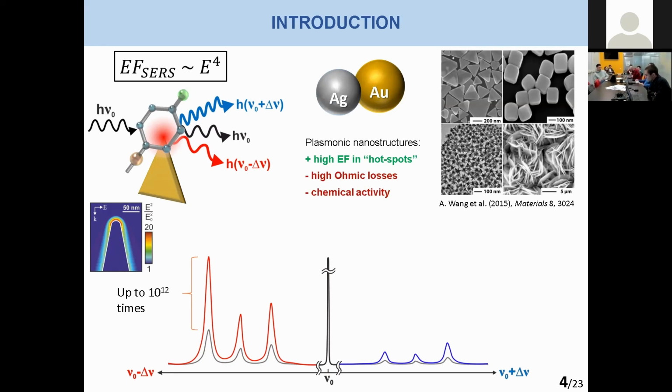But the use of metallic nanostructures has some disadvantages. First is heating of metal nanostructures due to high ohmic losses in metals, which, with the difficulty in direct measurement of heating temperature values of nanostructures during SERS measurement, can lead to thermal destruction of adsorbed molecules.